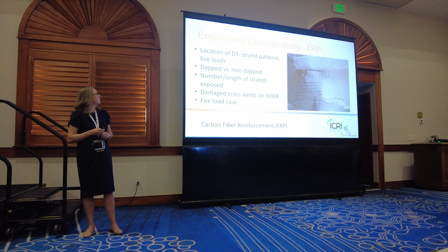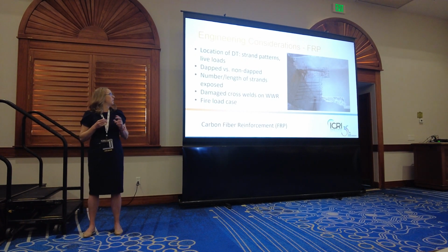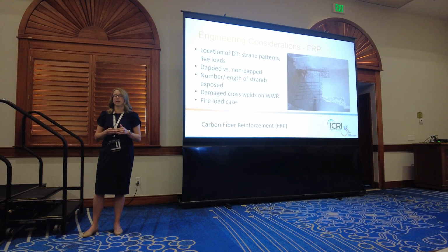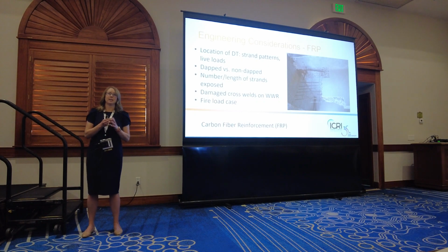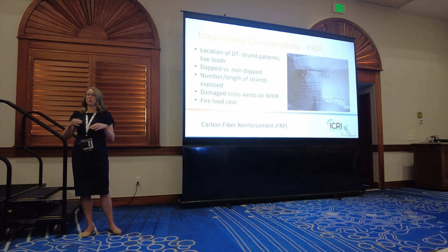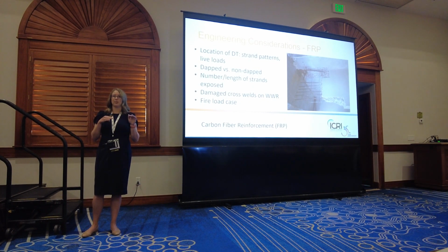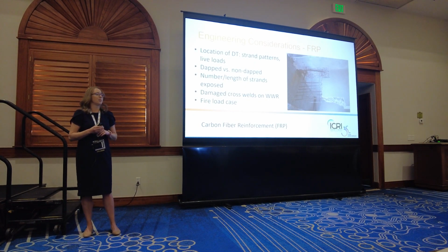Dapped versus non-dapped, we kind of hit on that previously. And then really one of the biggest ones is the number and length of strands that are exposed. So the further you get away from bearing, the more of your pre-stressing force you lose. And that needs to be considered not only along the length of the member, but also along the height. So I'm sure many of you in the room have seen funky geometries, and we're always trying to keep as much of the native material there as possible that is in good condition. Obviously, all the unsound stuff needs to come out. But so just kind of thinking through some of those different patterns and how does that affect the loss of pre-stress.